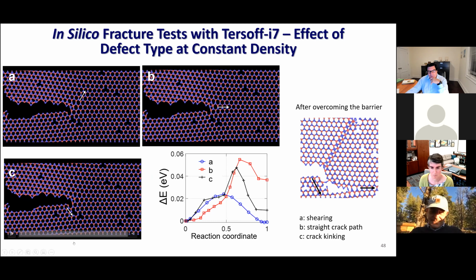So you are computing essentially the energy that is being delivered for propagation of the crack. The atomic processes are illustrated here. Could be the shearing of the lattice in this particular scenario with some vacancies in the neighborhood. Or it could be the cleavage, the sequential breaking of bonds, or it could be going down and then cleavage. And the reason why it does this in this scenario, because we use nudged elastic band, you take this initial configuration and then you shear, is that the lowest energy barrier is the shearing for this particular instance. Now, you may have many different instances depending on the arrangement of defects.